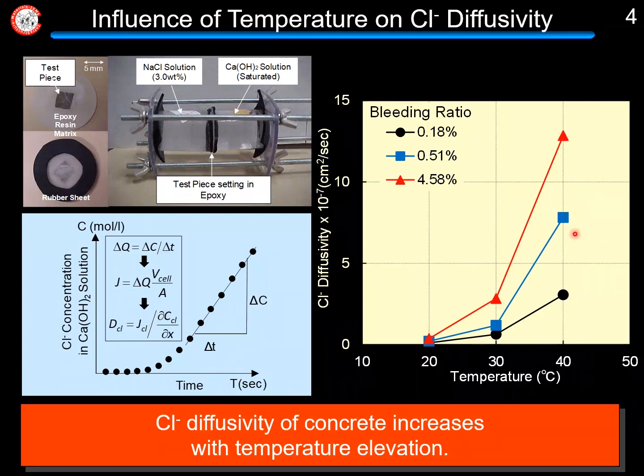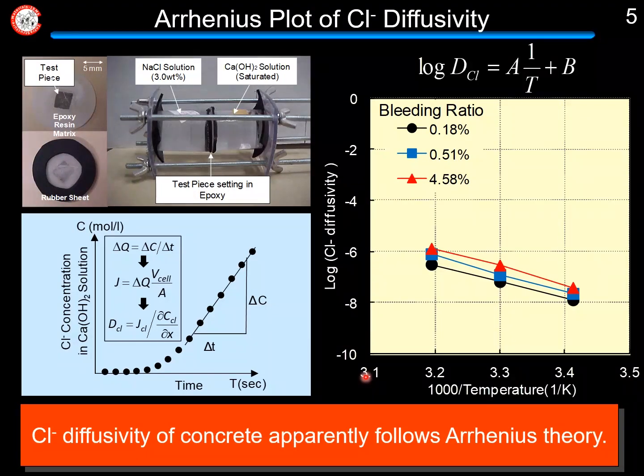As shown in this graph, it was confirmed that the chloride ion diffusivity increases with temperature elevation. Also, this figure shows the relationship between the logarithm of diffusivity and the reciprocal of absolute temperature, called an Arrhenius plot. From this, we can see that the chloride ion diffusivity follows Arrhenius theory.